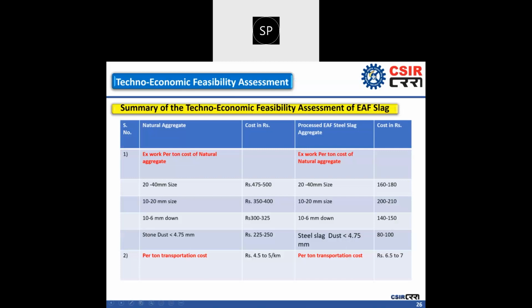So normally the cost of the processed slag aggregate is around 50% cheaper than the natural aggregate available in that region. Therefore this material is economical, at least in all the nearby regions. Besides that, the per ton transportation cost is slightly higher in comparison to the conventional aggregate. Since it is a bit heavier, the per ton transportation cost will be between 6.5 to 7 rupees per kilometer, while it is 4.5 to 5 rupees per kilometer for the natural aggregate.